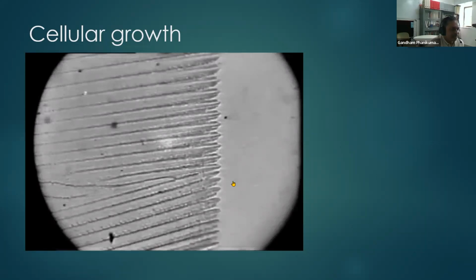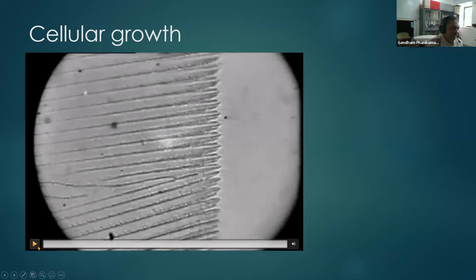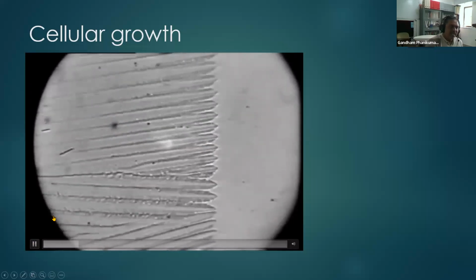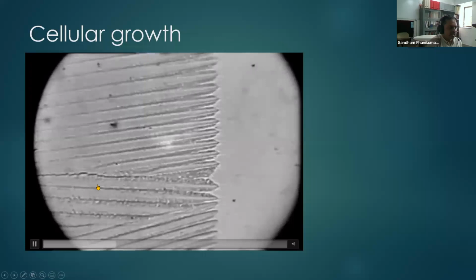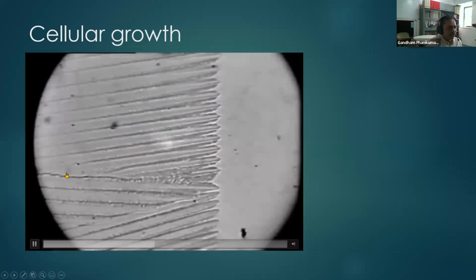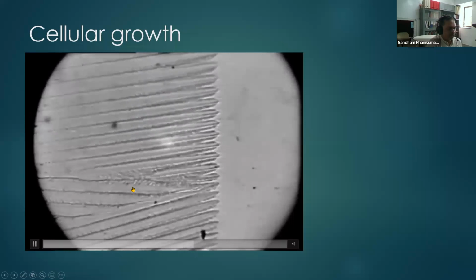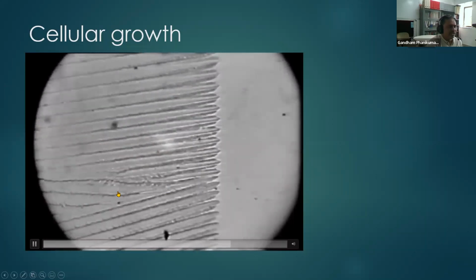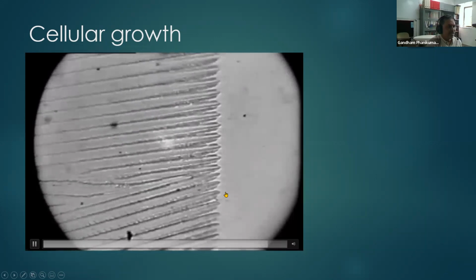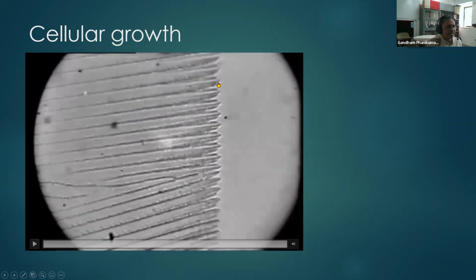Okay, so Mullins-Sekerka instability is basically, originally if it starts as a planar interface, due to thermal fluctuations, the interface will break, and therefore it will then form cells. The cells are very stable structures, and they can also have some orientation. So you can see there's a grain boundary between two cells because the orientation of the cells is different. And you see that there's a triple junction of the grain boundary here, and then there's a grain boundary that is growing this way. And this is the solid-liquid front. This is all liquid, and this is all solid. Okay. Now, this is a video made of an analogous material, a polymer material, but the concepts that are seen are applicable,